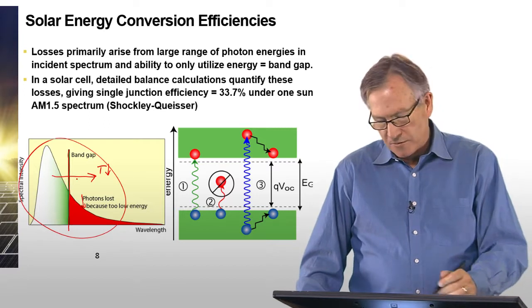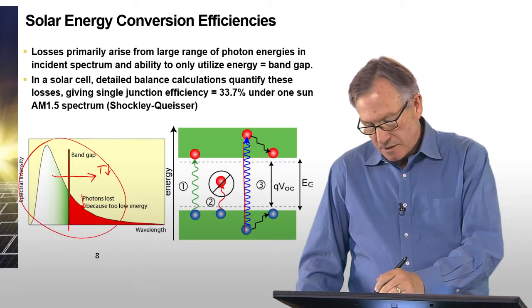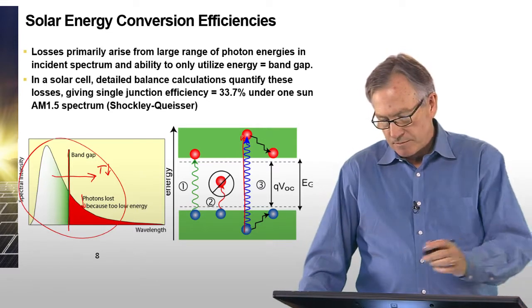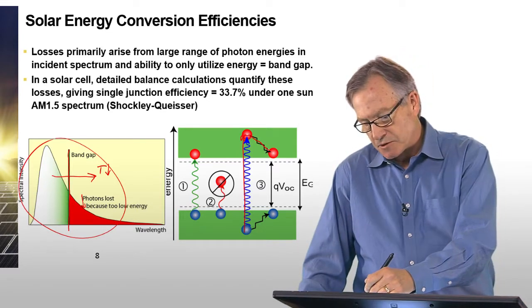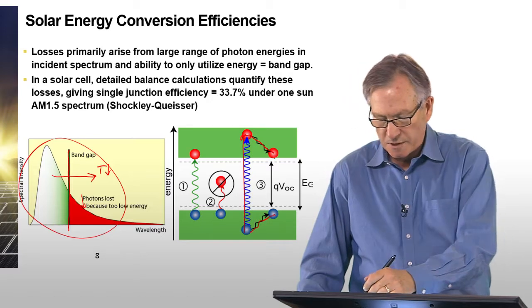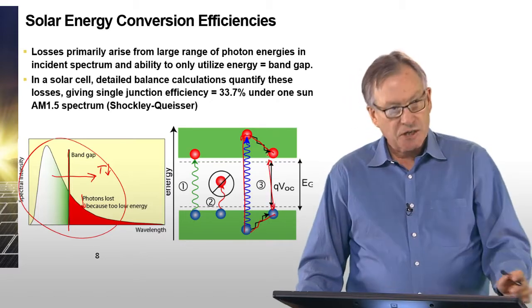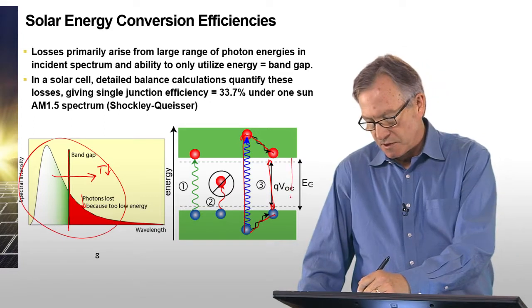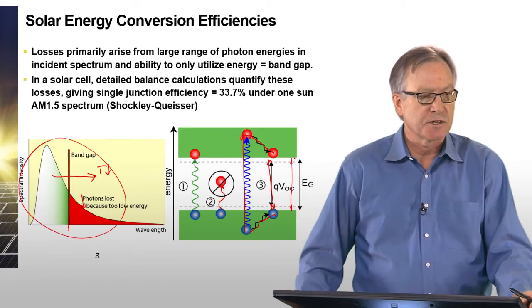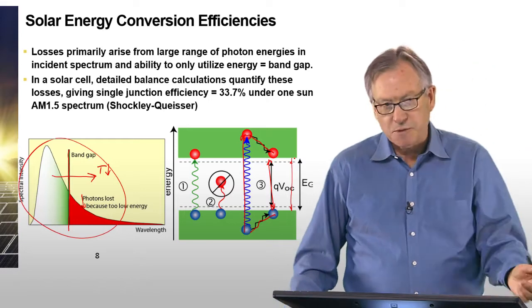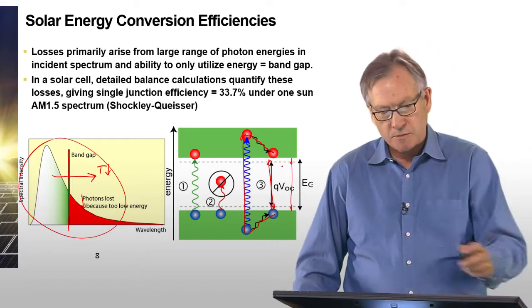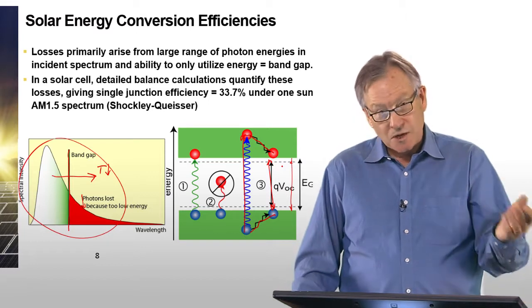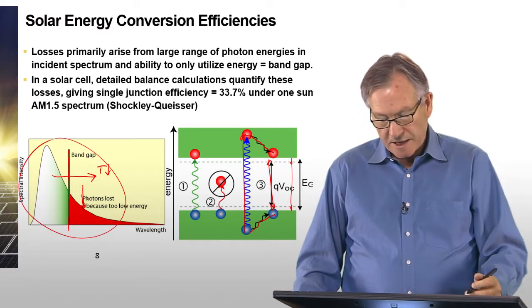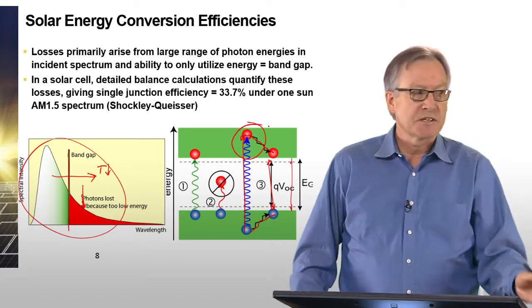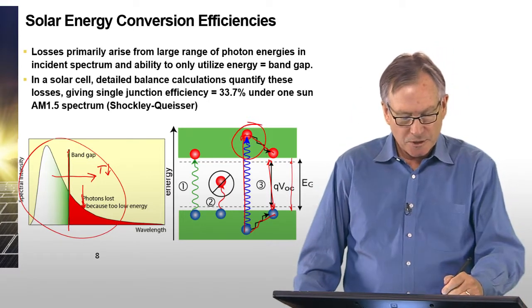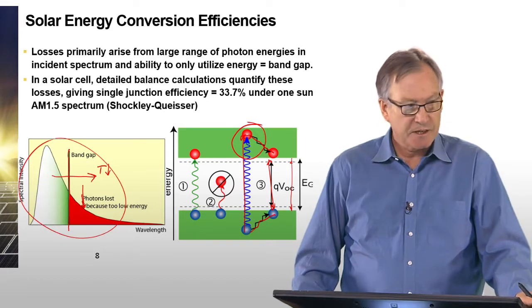Now, as I mentioned before, and if you look at the curve on the right, for photons that have energy greater than the band gap, the excess energy of the carriers is quickly lost due to thermal processes, and you only collect energy at the band gap, and actually somewhat less than the band gap. It's a small fraction below the band gap that you can actually collect energy. In other words, the open circuit voltage is determined by the band gap minus some fixed amount. So there are two losses. One is the loss of the photons below the band gap. The second is the loss of the excess energy of the photon above the band gap. And so you only really utilize photons at the energy of the band gap.